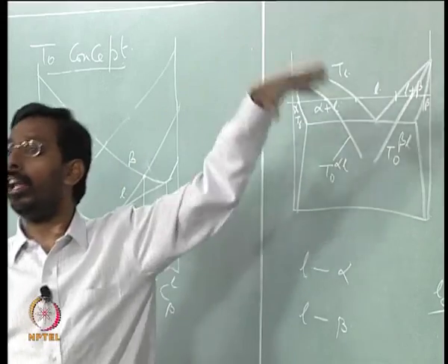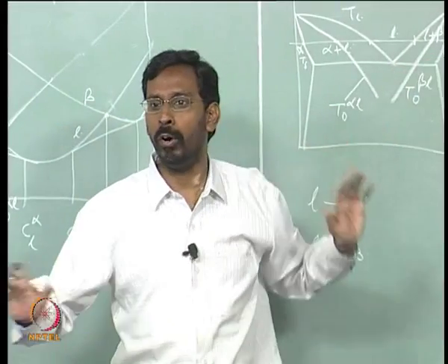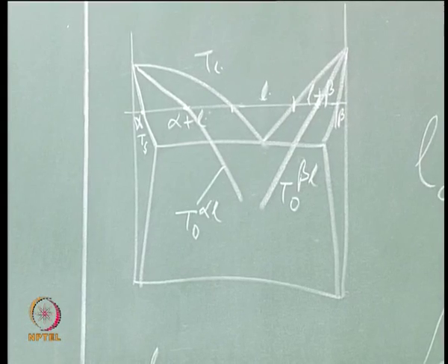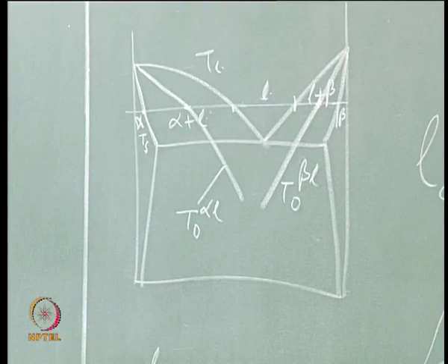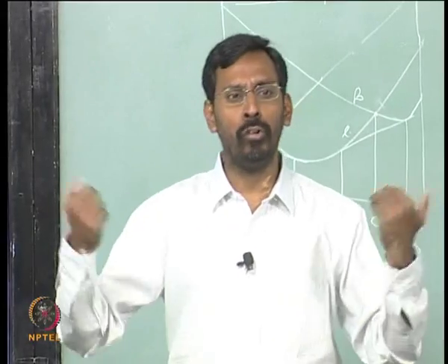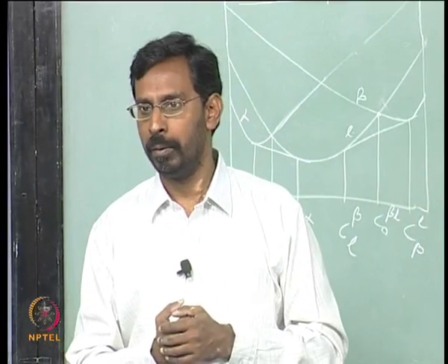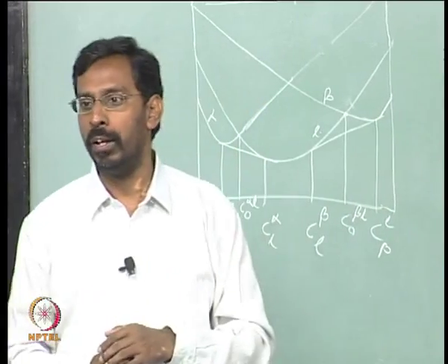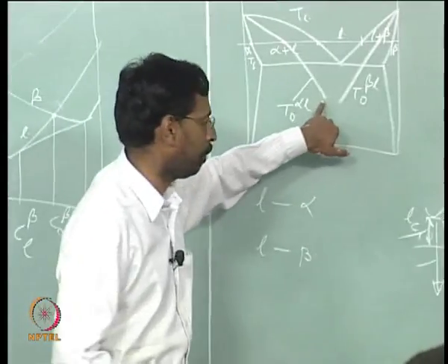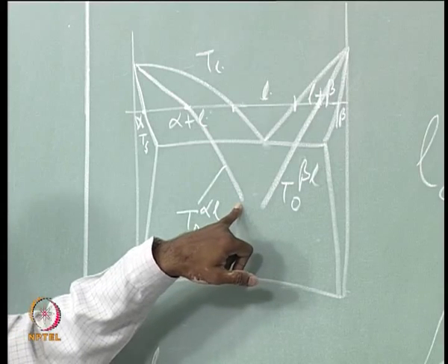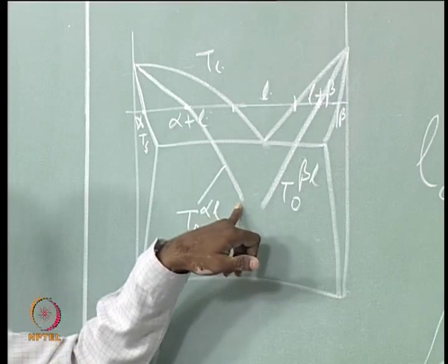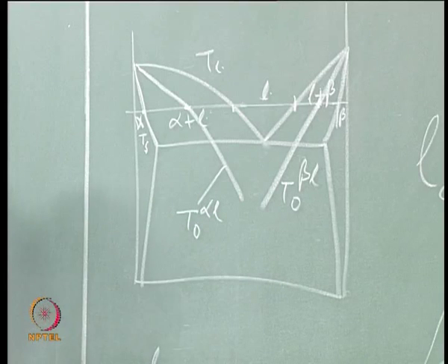You may also calculate the phase diagram, I do not say no, the whole phase diagram can be calculated from free energy. But in a large number of cases the whole phase diagram can also be obtained experimentally by doing thermal analysis. By doing thermal analysis or any other experiment you will not be able to get this. This has to be calculated from free energies. Of course, you possibly need some experimental data to get the free energy.